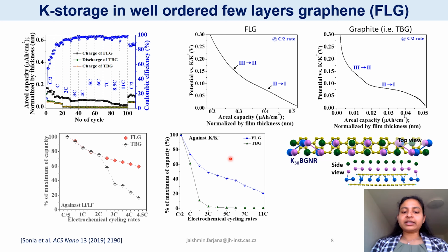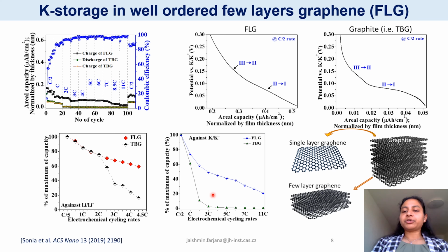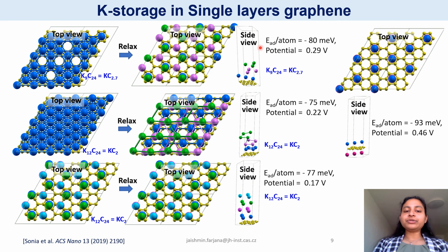And we also tested the rate capability for the potassium and for the lithium, and we have observed that for the potassium, the change in rate capability is dramatic when we go from the bulk to the few-layer graphene. We lost almost all the capacity, it becomes almost zero for graphite when we are at the higher current rate. So for the potassium storage, specifically going from graphite to graphene is very important. We also did DFT-based calculations on the potassium storage in single-layer graphene.